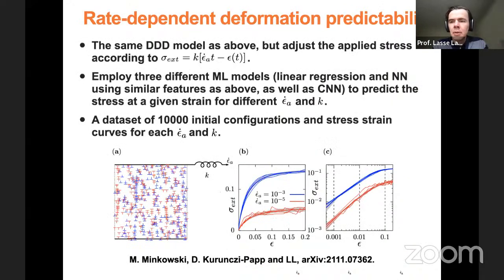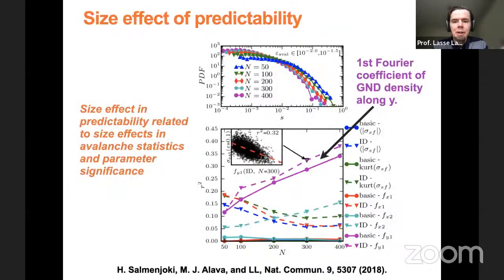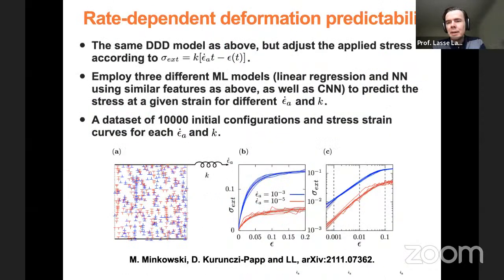Okay, so that was all. I don't know if I said it very clearly, but all of that had to do with a specific loading mode of your dislocation system. You quasi-statically ramped up your stress, so it's like an infinitely slow deformation process, if you like. But here, what we want to study is the role of applying a finite strain rate. So your deformation now proceeds at some rate that you specify, and then you can study what happens to this predictability as you change the rate, so how fast you deform your crystal.